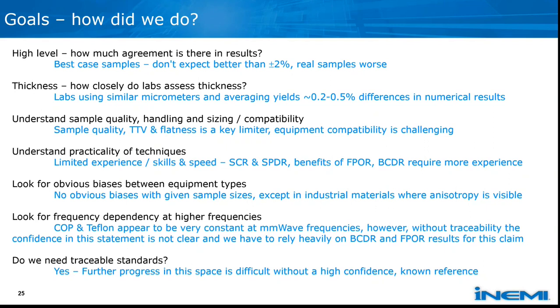Thickness - how closely did the labs assess thickness? It turns out the labs were all using very similar micrometers for assessing thickness, and our procedure described a method where you average the thickness measurements of 4 locations on the sample, specifying exactly where those locations were. Because of that, we yielded a very tight tolerance on our average thickness, ending up with something on the order of 0.2 to 0.5% differences in the final numerical results for the thicknesses of each sample. That's really pretty good.